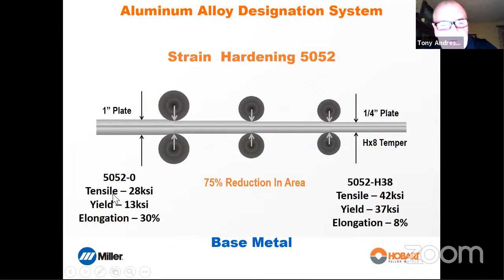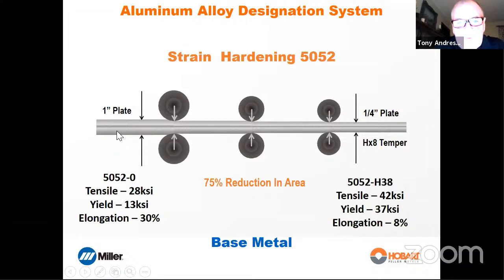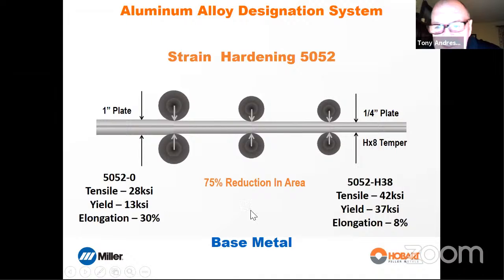Well, this example is a 5052, which is 2.5% magnesium. And it's in an O temper. See, 5052-O, that means that's the annealed strength. The O means that it's annealed. The annealed strength of any aluminum alloy is its lowest strength. Sometimes people call it dead soft condition. Right, so in this case, we take a 1-inch plate of 5052 at its lowest strength, and its minimum tensile strength is guaranteed to be 28 KSI. All right, so now we put that plate, a 1-inch plate, through a set of rolls, and we reduce its cross-sectional area by 75%. We take it down to 1/4 inch. All right, we have now strain hardened that material to an H38 temper. And we've increased its strength from 28 KSI to 42 KSI.